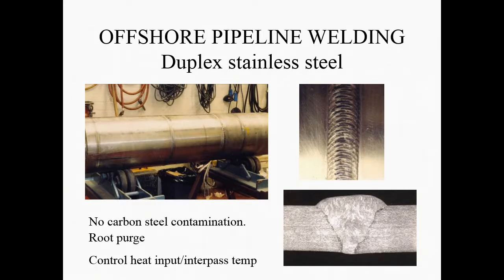So how can you avoid that? Well, first of all, do not use any tools that are made from carbon steel, or if they are made from carbon steel, they must be faced somehow with stainless steel. And also something that is very common, the use of grinding discs. Make sure that grinding disc hasn't been used before with carbon steel. That's one measure that is very important.